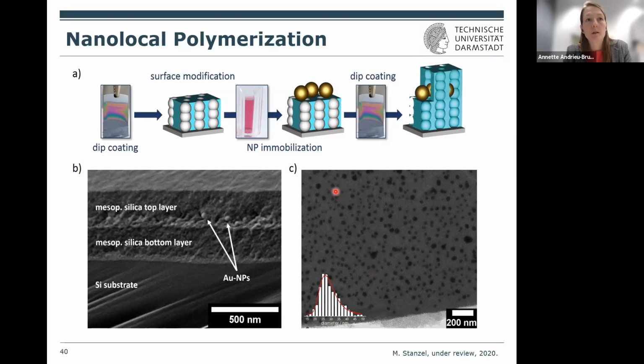That's maybe better by using a planar gold surface. You can use that as well, and then use basically plasmon resonance spectroscopy, but misuse it for polymerization, the setup. That's what we do as well. The problem there is we can show that this works. So you polymerize, that's nice. But the problem is to really analytically show and convince everybody that this stays nanolocal. This is the advantage of the particle, to just show, okay, you take all the data together and then it's very probable, yes, it's a nanolocal polymerization. So basically, in terms of which aim you would have with these nanolocal stuff, you would have to adjust a little bit how you go there. And we have two other techniques currently in development doing the same by basically misusing high resolution microscopy techniques.